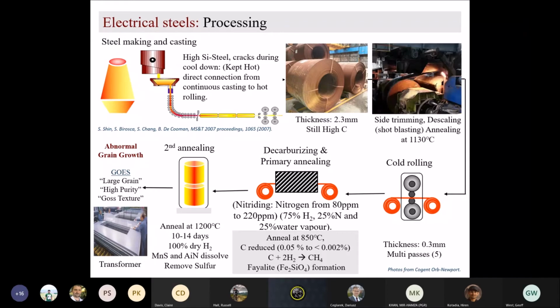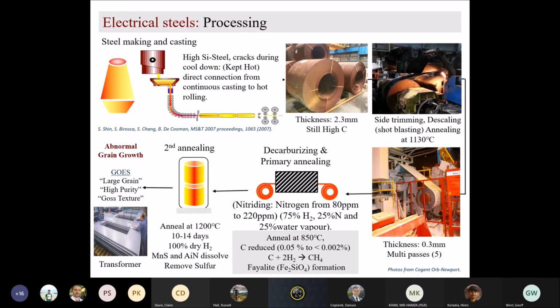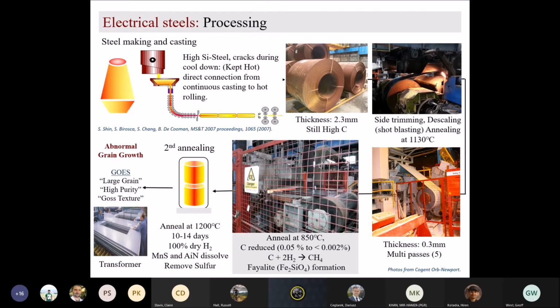Then it is ready for cold rolling. After side trimming and descaling, you will have a much cleaner, oxide-free steel, and it will be reduced to 0.3 millimeter, which is very thin, normally in 5 passes, as Cogent Orb-Newport was doing. After the hot rolling and cold rolling are finished, we don't need carbon anymore. We need the carbon for providing toughness and strength for the material to be hot rolled and cold rolled. After that, we don't need carbon, otherwise it will cause a lot of trouble for the magnetization process.